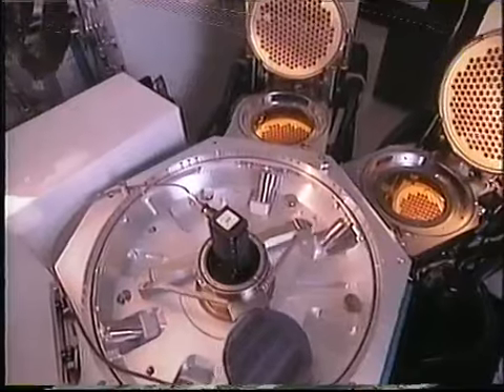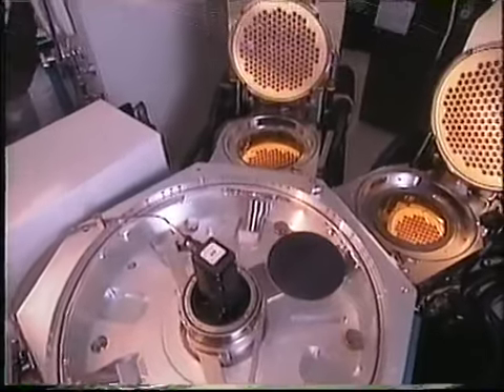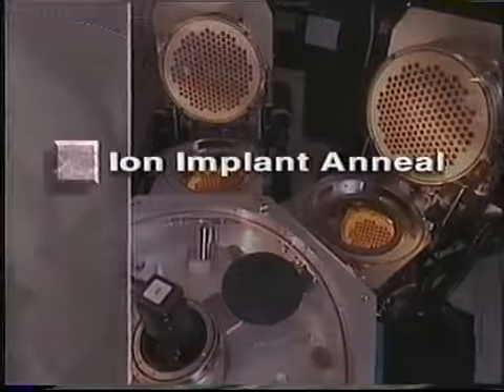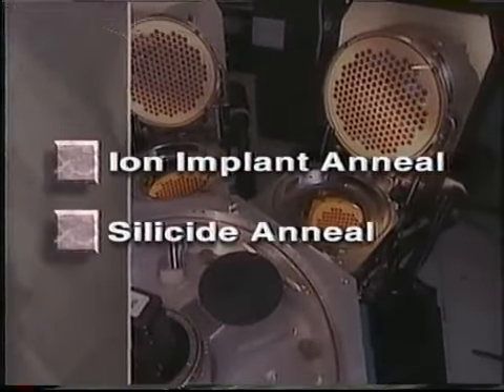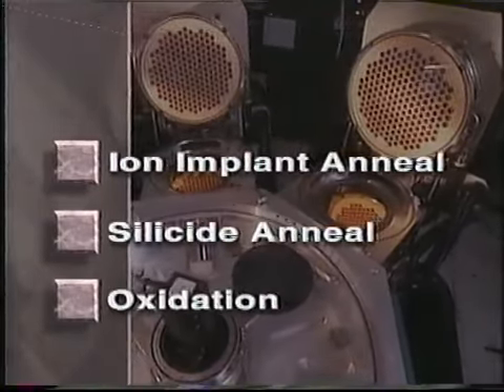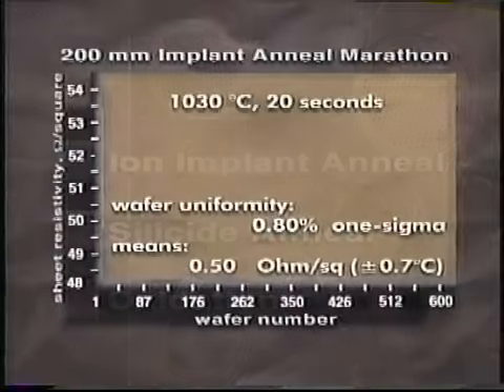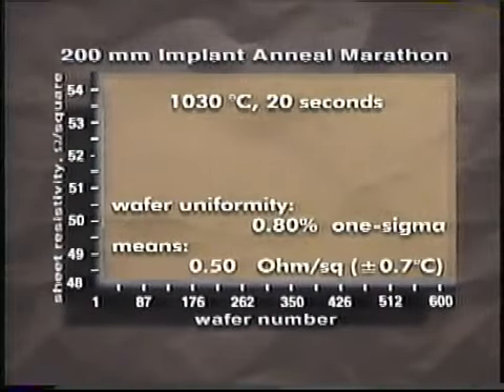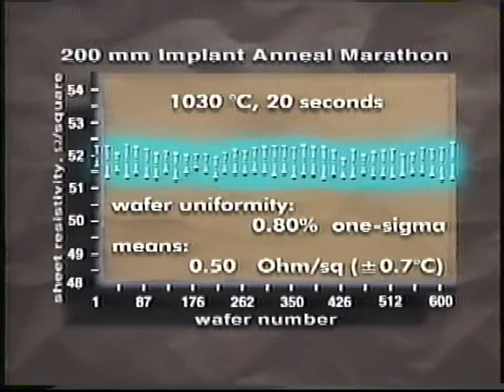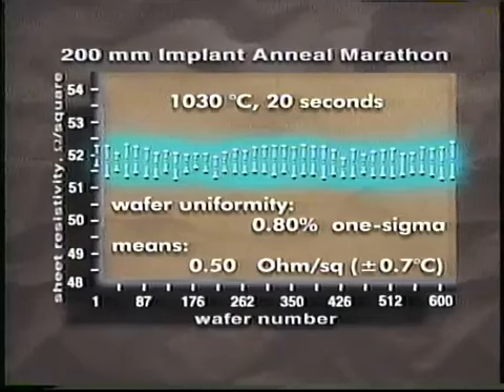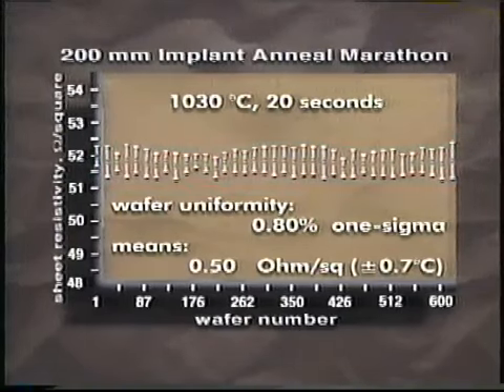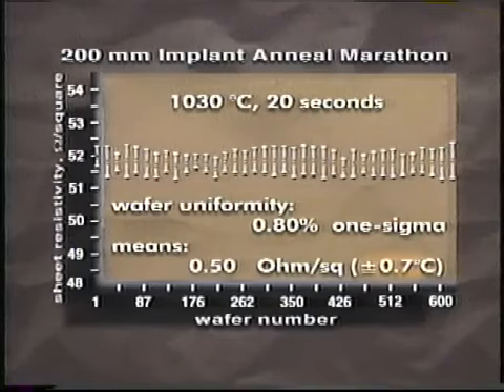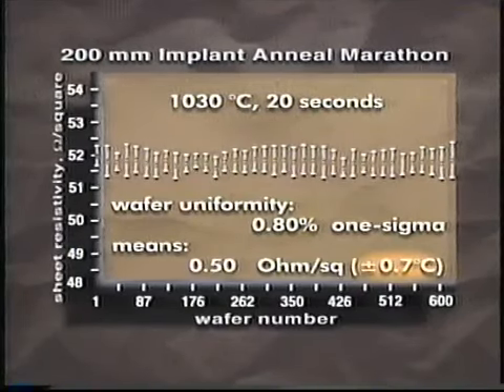The 3 major applications for the RTP Centura system are ion implant anneal, silicide anneal, and oxidation. Results on source drain implant anneal show more precise control of L-effective dimensions, a requirement for submicron devices. Multi-point temperature measurement ensures wafer-to-wafer repeatability of less than 1 degree C.